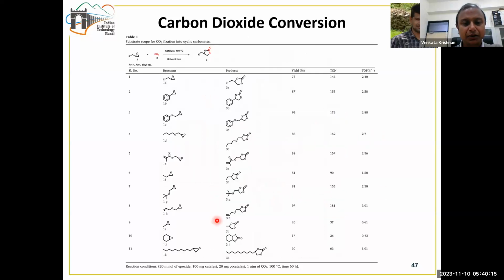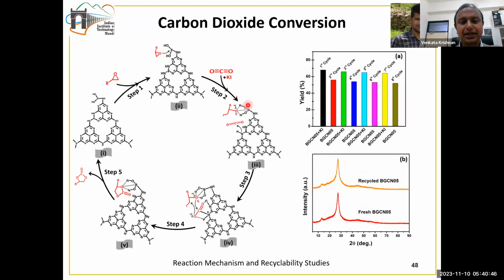Then we examined the substrate scope of this reaction by trying different reactants having different substituents, some with electron withdrawing property, some with electron donating property, and some are aliphatic in nature and some are aromatic in nature. So we have tried different substituents and examined the substrate scope, and we were able to successfully demonstrate that our catalyst is generic in nature, which can act with different types of epoxide based materials. Then, based on our experimental results and by looking at literature, we have proposed a mechanism, and we found why this catalyst is quite active for this carbon dioxide conversion.